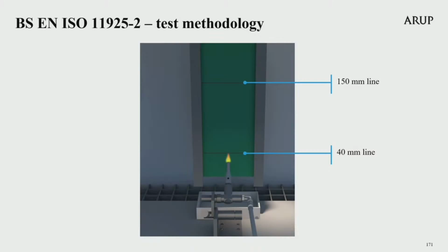The bottom blue line is the 40 millimetre line where the flame is applied for a surface exposure test, and the second line marks 150 millimetres above the flame application point. If the flame application time is 15 seconds, then the end of test is 20 seconds to allow 5 seconds of observation time. If the flame application time is 30 seconds, then the end of test is at 60 seconds, allowing a further 30 seconds observation time.